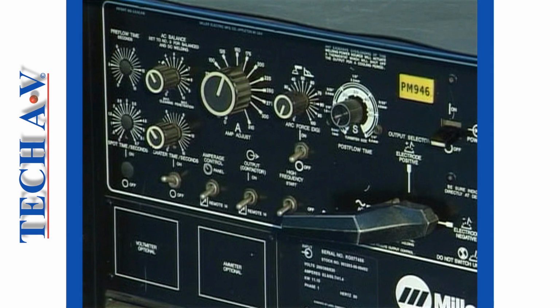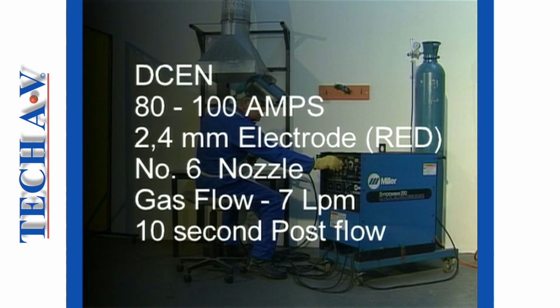The following optimum setup should be made on your equipment for this exercise. Current type is DC set on straight polarity. Welding current set to between 80 and 100 amps. Use a 2.4mm thoriated red electrode. Fit a number 6 nozzle. Adjust the gas flow to 7 liters per minute and allow a 10-second post-flow.